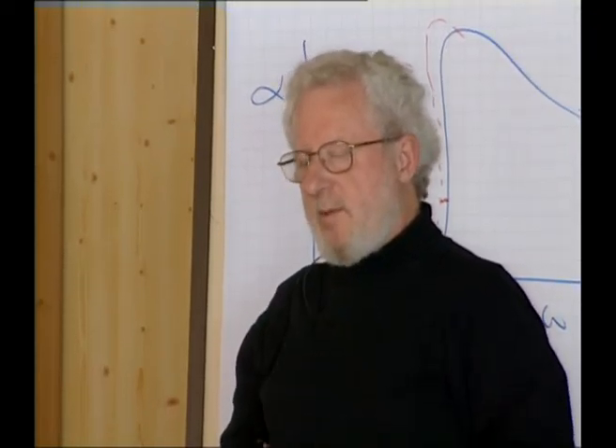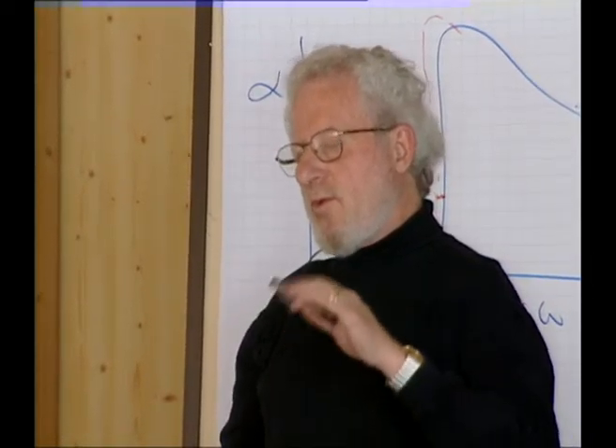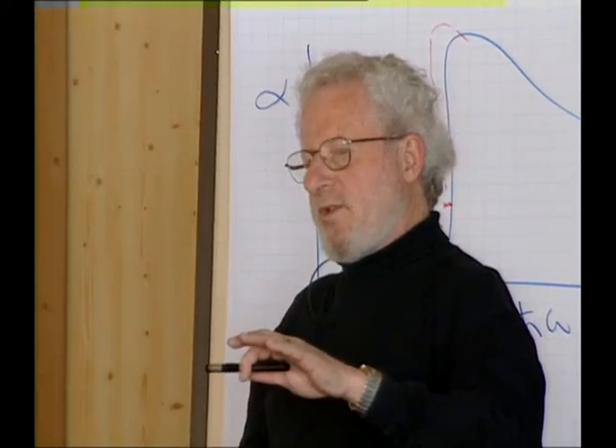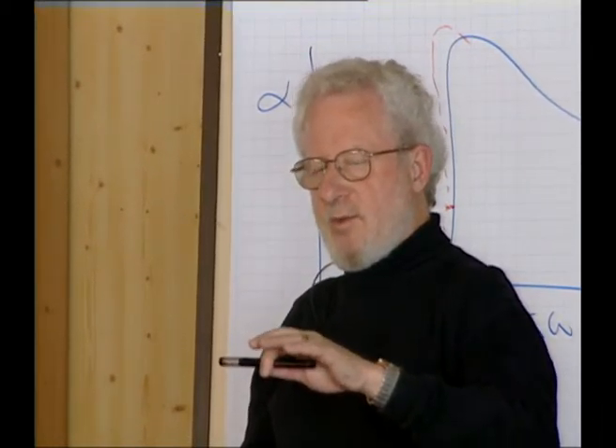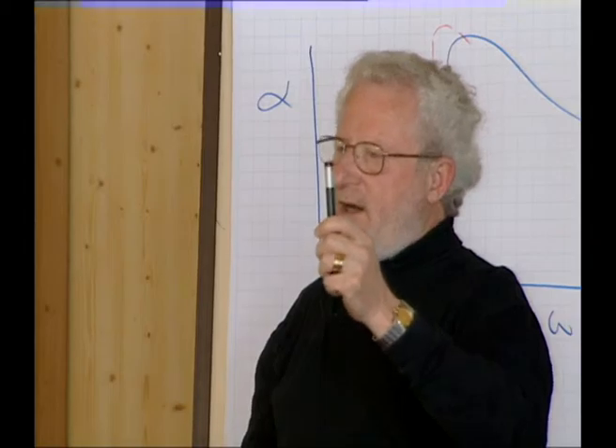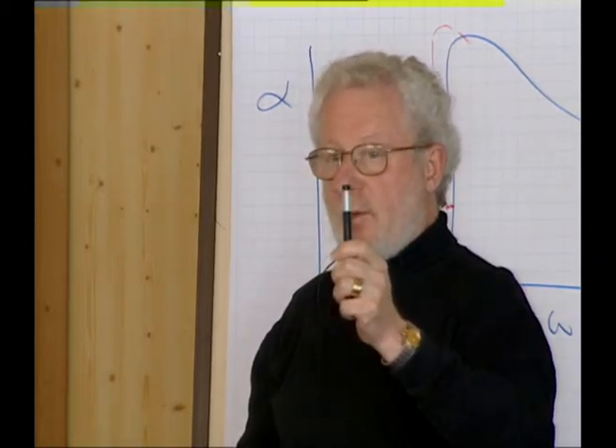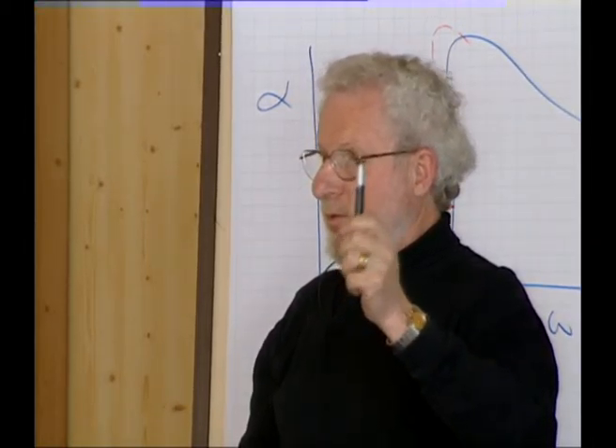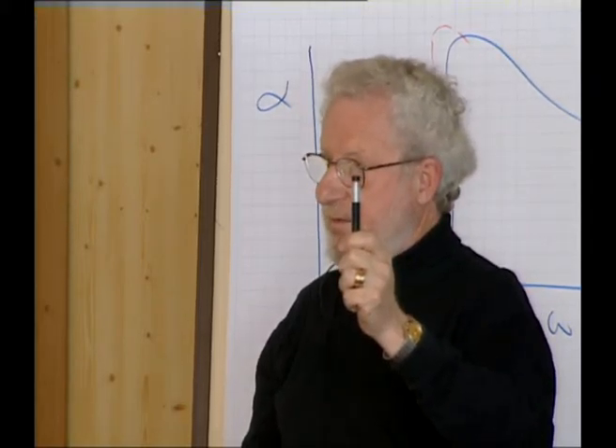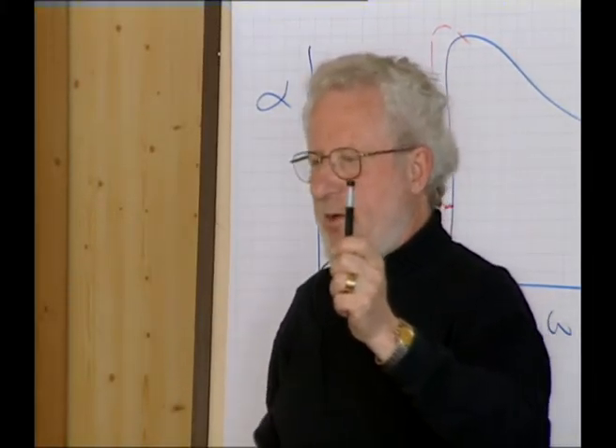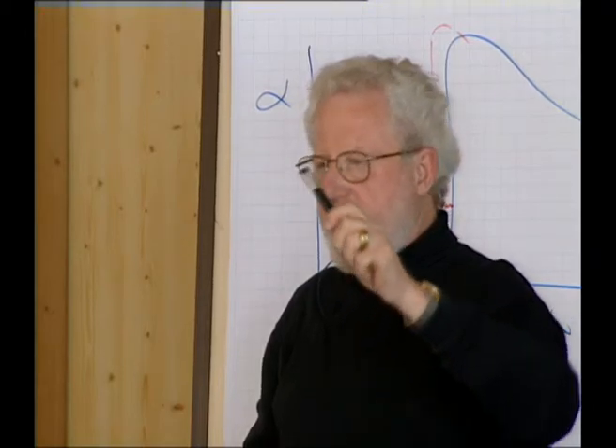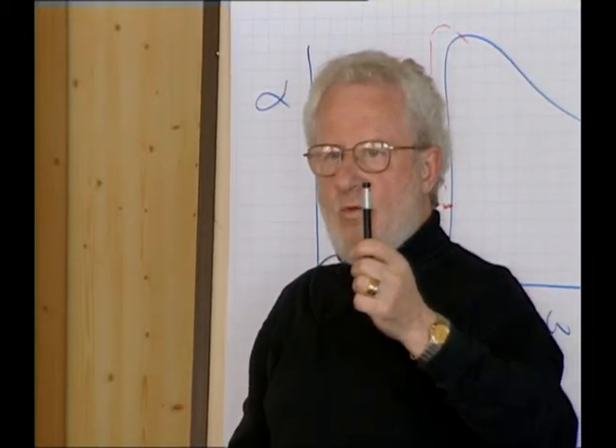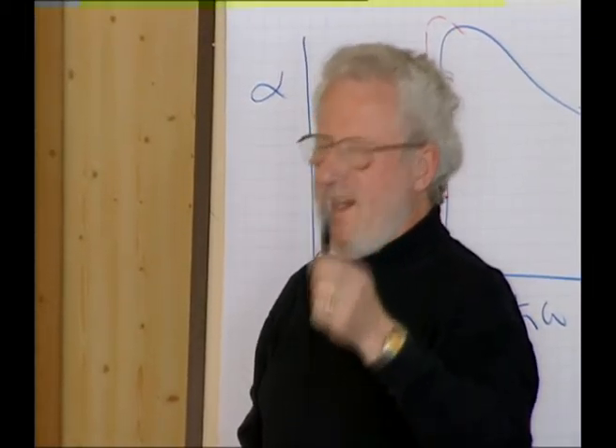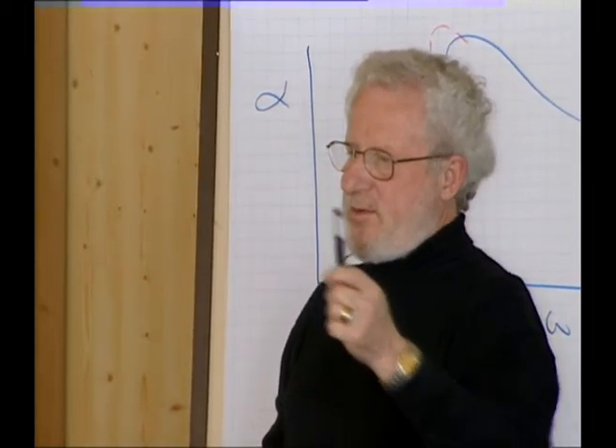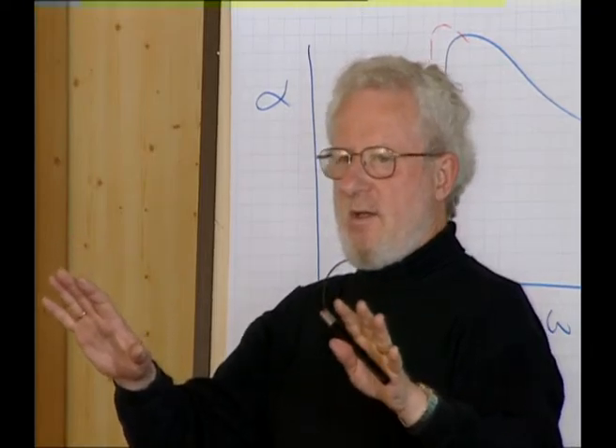So the next step that people have done is to have a polymer with a high glass transition temperature, do the poling at high temperatures, but now have an additive in there or have a polymer in there which is cross-linkable. So you pole it, and then you cross-link it. Maybe by UV, I don't know, somehow you cross-link it. And now these dipoles cannot relax, and so now you've frozen in the orientation of these dipoles. That whole methodology has been heavily explored.